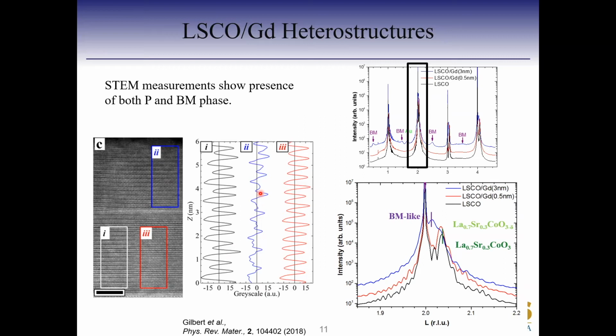So you can look at the cross-section using this technique, but to look at it in a lateral manner, how exactly this brownmillerite is forming, that's not very easy to do with TEM studies. In addition, this material is extremely sensitive to the oxygen ion, as we talked about. So there has been a question raised: when you do TEM sample prep, do you add more oxygen vacancies in this material? So that leads to the brownmillerite transformation, or can actually affect this distribution we are seeing here.